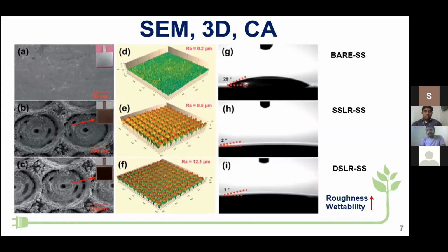We can see from figure G that it is for the bare stainless steel substrate, whose contact angle is about 29 degrees, whereas for single side it is about 2, and for double side it is about 1. So laser radiation is useful for creating rough texture as well as a superhydrophilic texture.